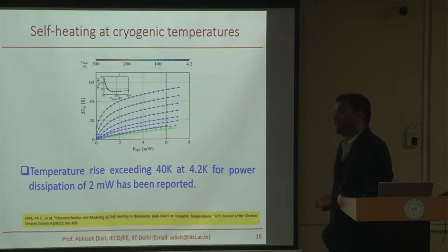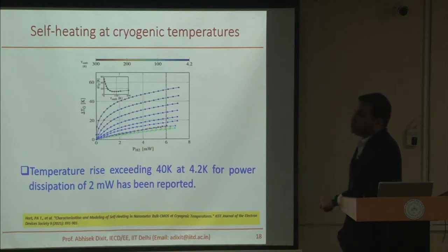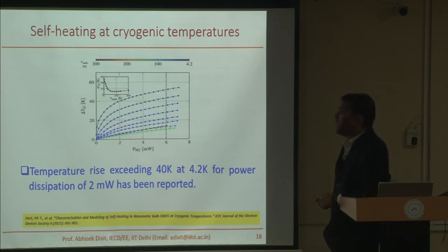We have searched the literature, not just us. This is a paper from someone else. A lot of people have had these issues, and there are multiple theories people are proposing. So we are not sure which way the thermal conductivity goes at cryogenic temperature. This is an active research topic. What we have observed from simulation is what we would call a poorer thermal conductivity at lower temperature.